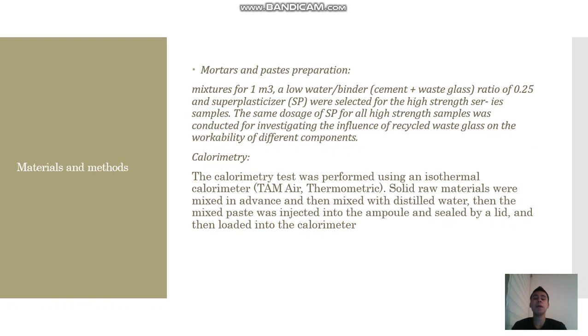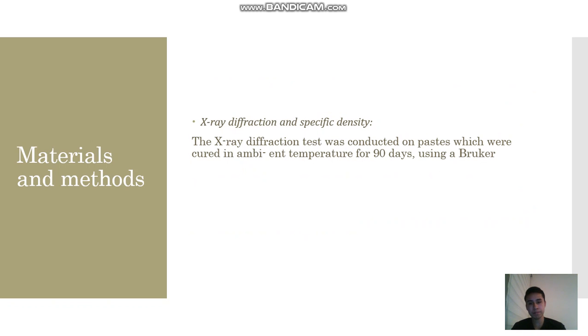Materials and methods: mortar and paste preparation, mixture for 1 cubic meter, a low binder, cement and waste glass, ratio 0.25, and superplasticizer. For the selected high strength sample, the same dosage of SP was used. For all high strength samples, tests were conducted investigating the influence of recycled waste glass on the workability and different components. Calorimetry: The calorimetry test was performed using isothermal calorimetry. Solid raw materials were mixed in advance and then mixed with distilled water. The mixed paste was injected into an ampoule, sealed with the lid, and then loaded in the calorimeter.